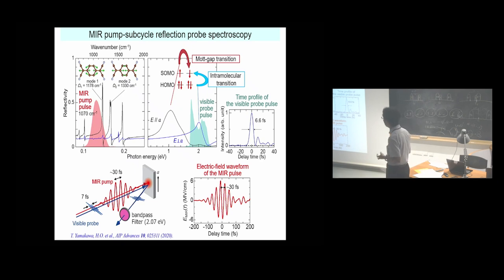This figure shows the polarized reflectivity spectrum. And this strong peak at 1 eV is the Mott transition, and sharp peaks below 0.2 eV are the out-of-phase edge mode vibrations. The band at 2 eV polarized perpendicular to the a-axis is the intramolecular transition from HOMO to SOMO in TCNQ. The intensity of this band reflects the charge and spin density in the TCNQ molecule. So we measure the reflectivity change of this band.